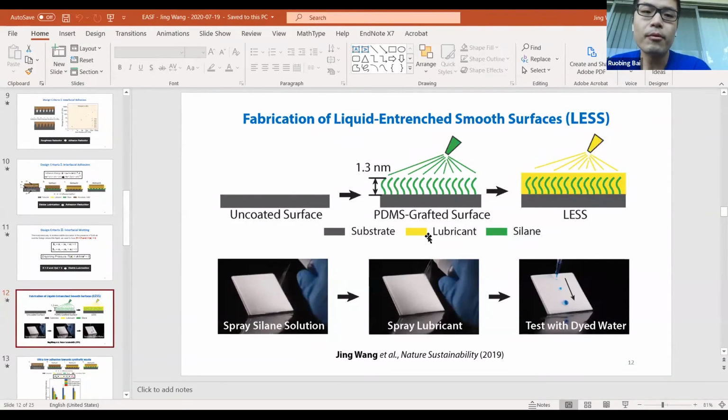But I think one scientifically interesting point is that if you have a silicon oxide bond, then especially with a lot of water, over time we know from glass this can have stress corrosion or crack propagation. For PDMS, you can expect a similar thing.